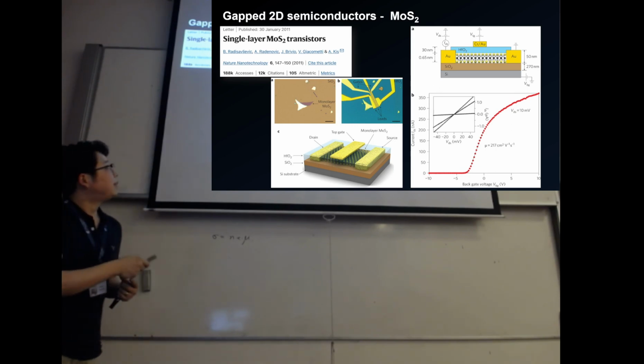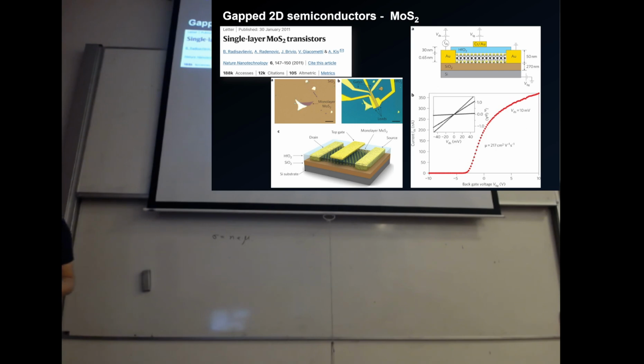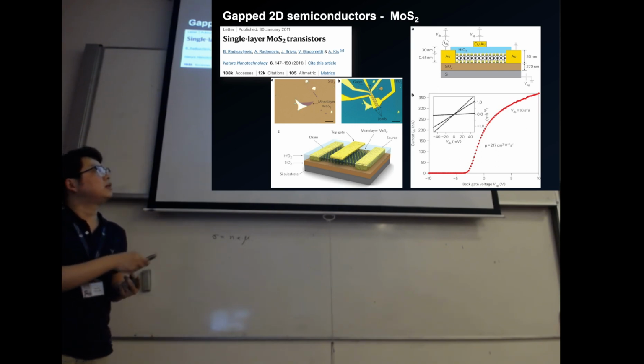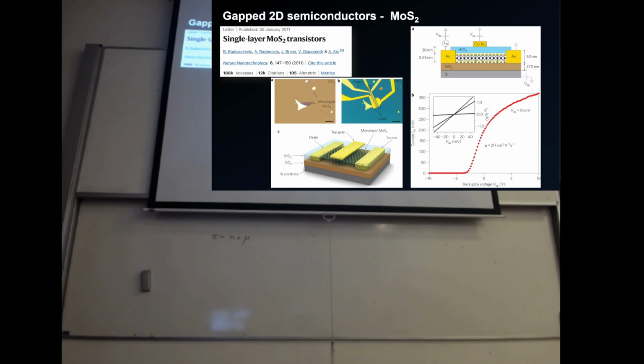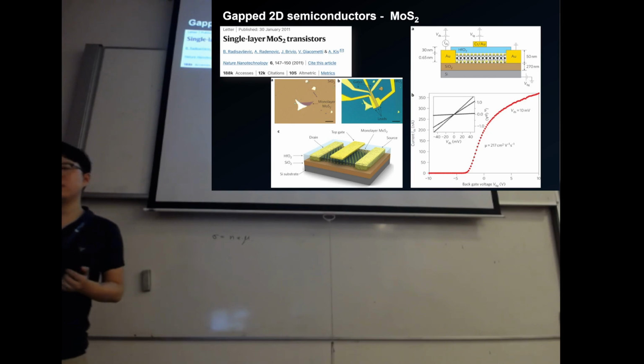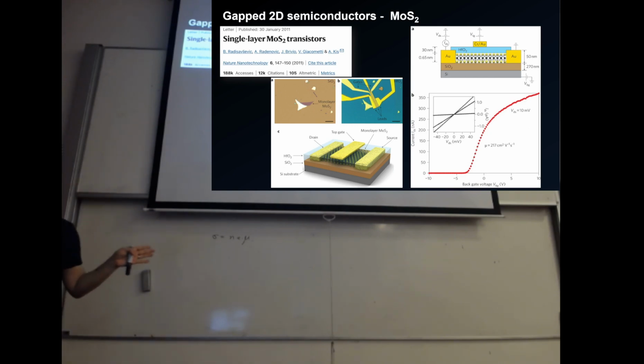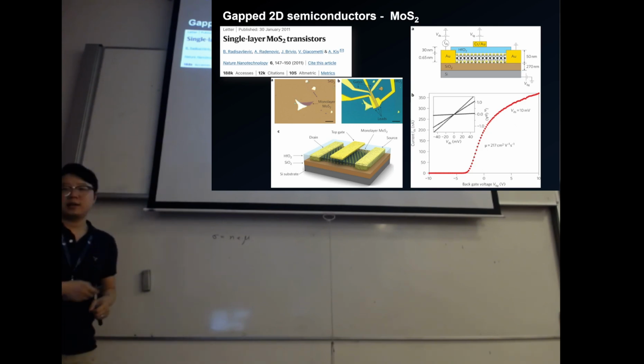Okay, and by just fabricating it into a MOSFET structure, Kis obtained a mobility of 200 at room temperature. And it got commented on by some other researchers from Columbia University because in the calculation there were some parasitic effects. So actually the mobility is only a few tens, but still it's very high at room temperature among all these known two-dimensional materials. As a semiconductor, the gap alone is already wonderful.